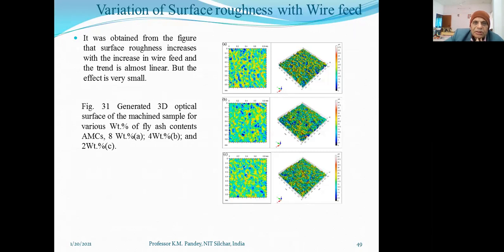So this is the variation of surface roughness with wire feed. Here it was obtained from the figure that surface roughness increases with the increase in wire feed, and the trend is almost linear, but the effect is very small. Figure 31 is the generated 3D optical surface of the machined sample for various percentage weight of fly ash content.